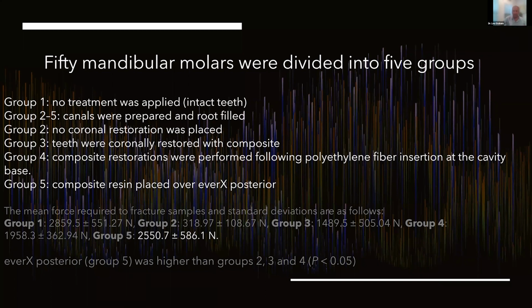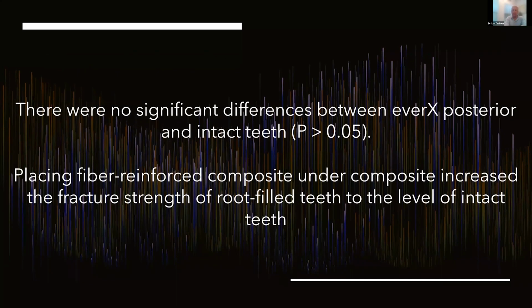Now, if you look at this, and I want to go over this really clearly, group 5. So a composite resin was placed over Everex Posterior. And why was this the ideal treatment? There were no significant differences between Everex Posterior and intact teeth. Placing this material under a composite increased the fracture strength of root canal filled teeth to the level of intact teeth, was their conclusion. So now, if you have a lot of tooth left, minimum parafunction, ideal occlusion, you have something here that could potentially minimize future fractures on root canal filled teeth.